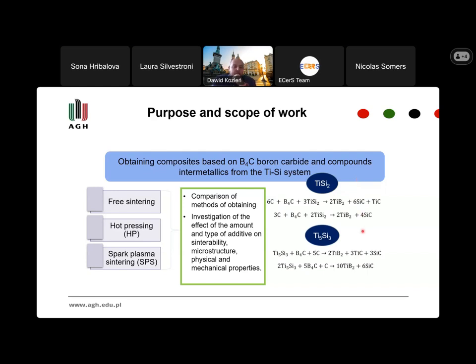For the starting, we use two composite systems. This system was titanium disilicide and Ti5Si3. So we assume two reactions. It was assumed that the dominant phases in the resulting product should be silicon carbide, titanium diboride, and titanium carbide.